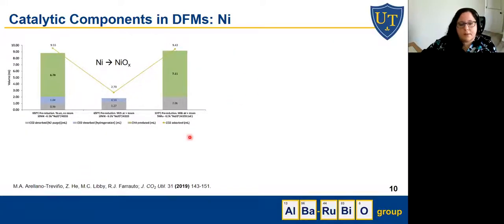Here in this paper, they show that when using clean flue gas with a nickel sodium oxide alumina catalyst, the activity and the production of methane was very high. But when flowing a flue gas that contains some air and steam, the activity dropped dramatically. And they found that this is because nickel becomes oxidized and is not easily reduced because of the high temperature required to reduce nickel.